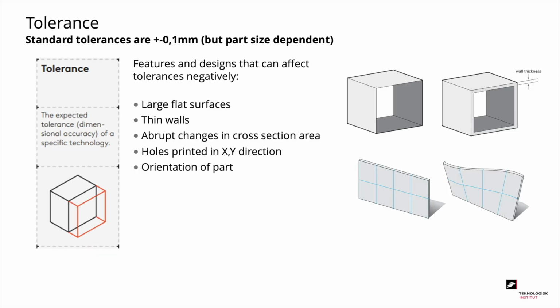Next up is tolerances. The standard tolerance is 0.1 millimeter, but it is of course dependent on the part geometry. There are some specific designs that you should pay attention to that negatively influence the tolerances. Try to avoid large flat surfaces and thin walls, and avoid abrupt changes in cross-section areas, as it will distort the part. Also pay attention to holes printed in the XY direction. They will be elongated.